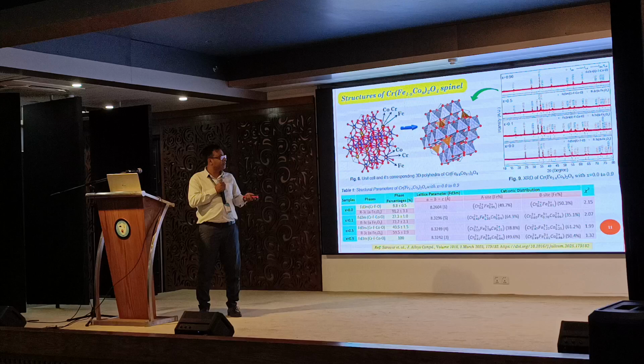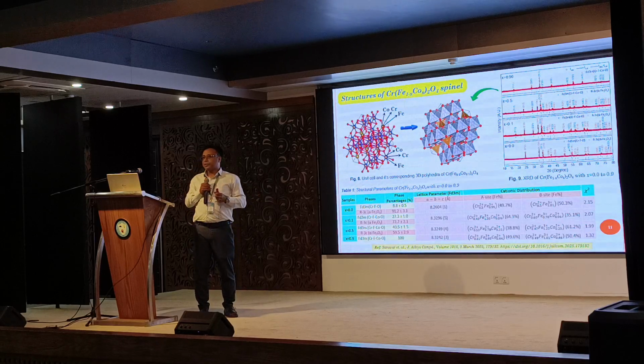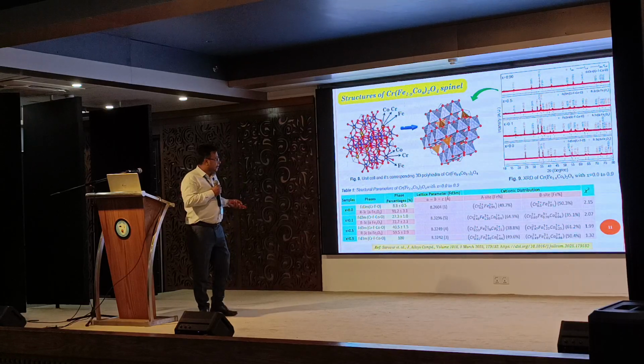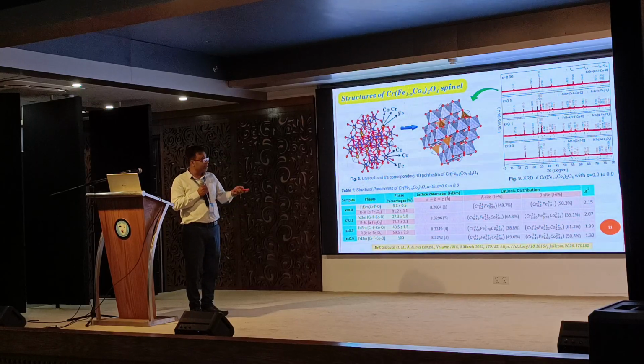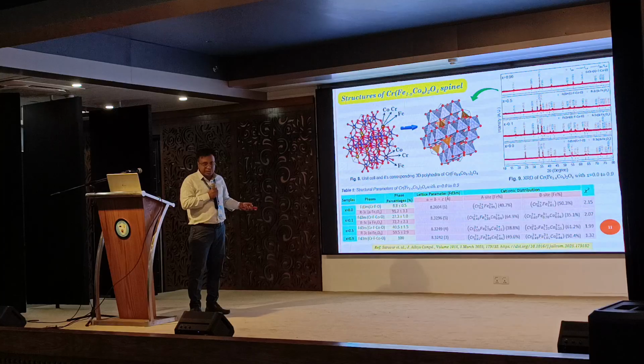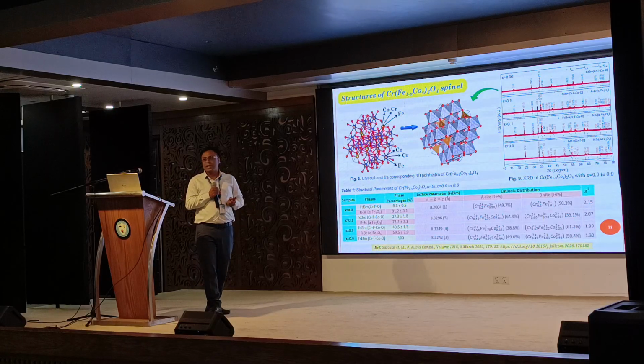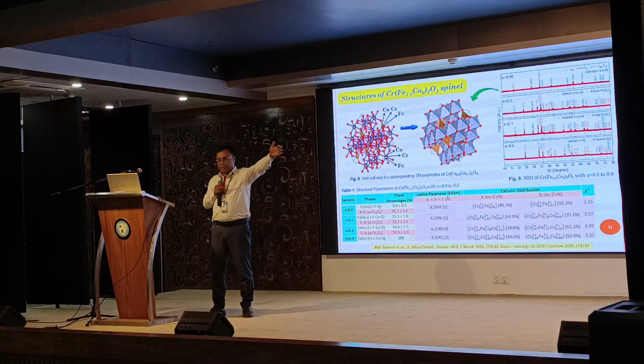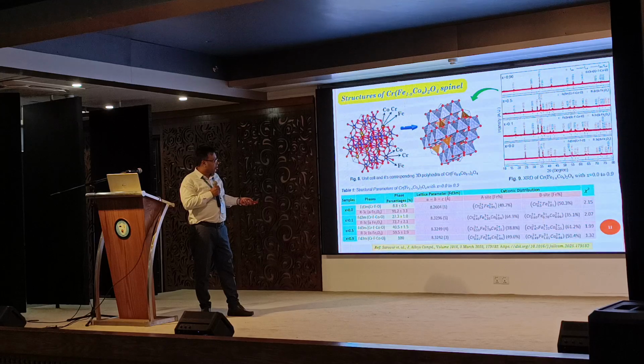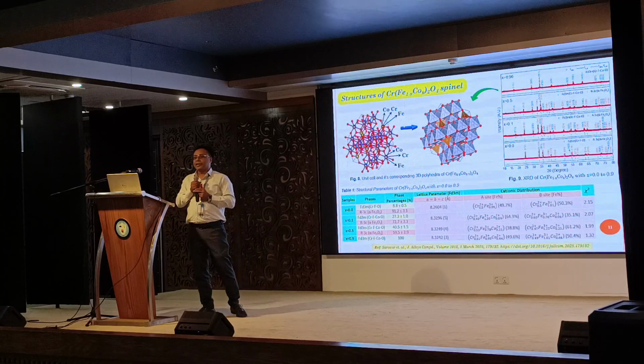After performing this, you will get the structure, whether the material is mixed spinel, inverse spinel or general, normal spinel. We confirm more things that you can also find from this, that is cationic distribution. The iron is displaced from the A site to the B site. Actually this material is like a window: you are going outside and you are coming from outside. You can control this by doping. So here also we found that iron from the A site shifted to the B site, and also some of the B site iron shifted to the A site. And this shifting actually improves or enhances the magnetic property.